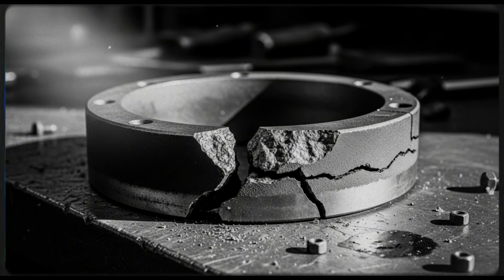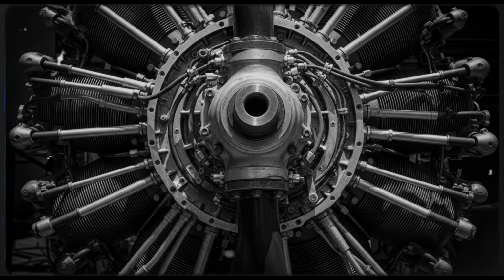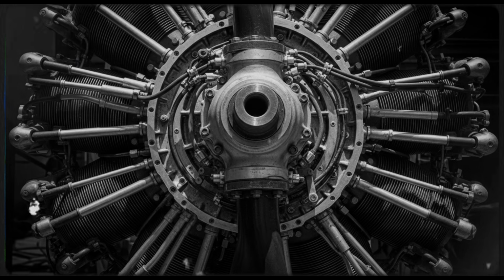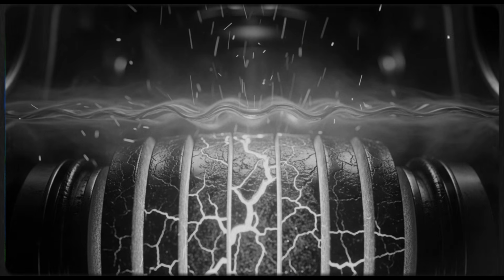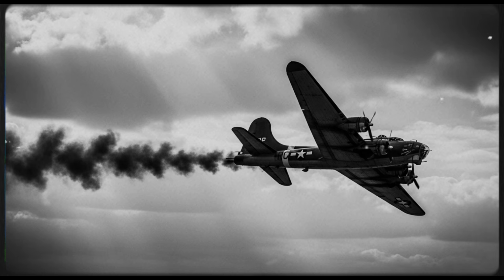And they are facing an absolute disaster. The standard cast iron rings, a design they'd used since the early 20s, were failing spectacularly. In a typical car, they might last 20,000 miles. But the military was now pushing the boundaries with colossal aircraft engines. We're talking 2,000 horsepower behemoths with 18 cylinders firing in a symphony of controlled violence, spinning at 3,000 RPM. Inside these infernos, with temperatures reaching nearly 1,200 degrees Fahrenheit, the cast iron piston rings were simply giving up after only 40 hours of operation.